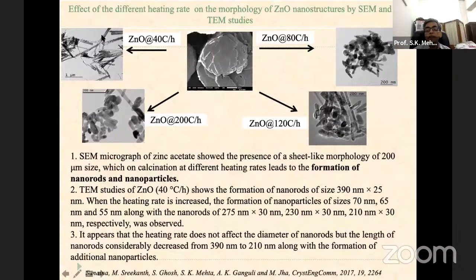The size is 390 nanometer by 25 nanometer. When the heating rate is increased, sizes of 70 nanometer, 65 nanometer, and 55 nanometer, along with nanorods in the range of 275 by 30 to 210 by 30, were observed. Okay, so this one can easily be understood.